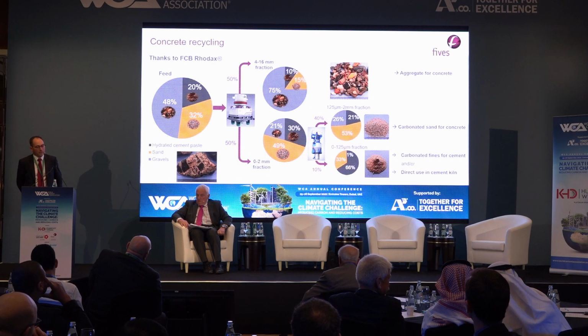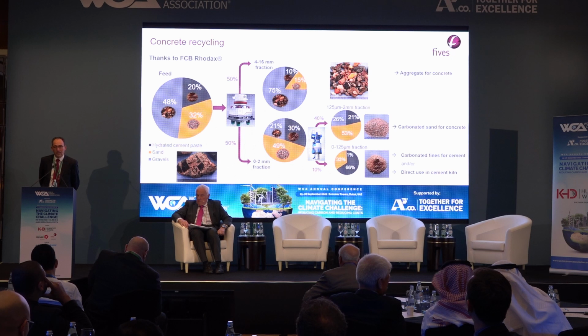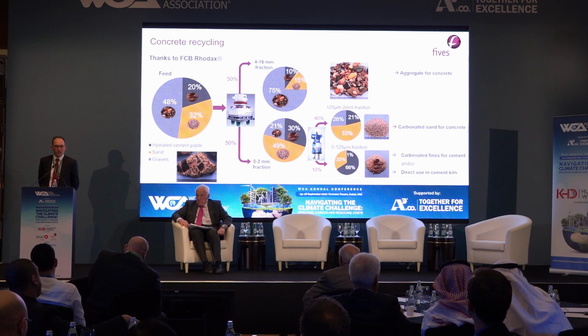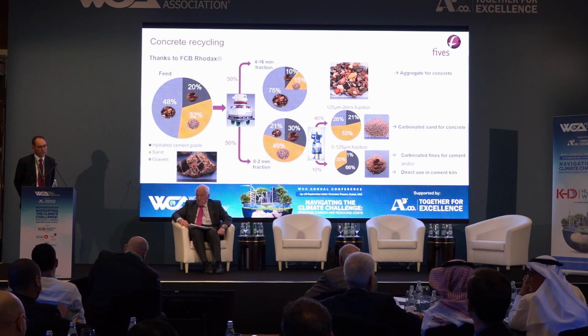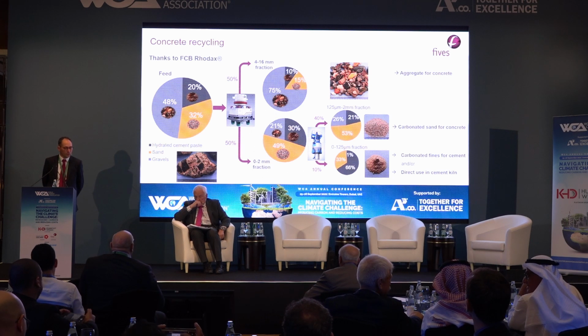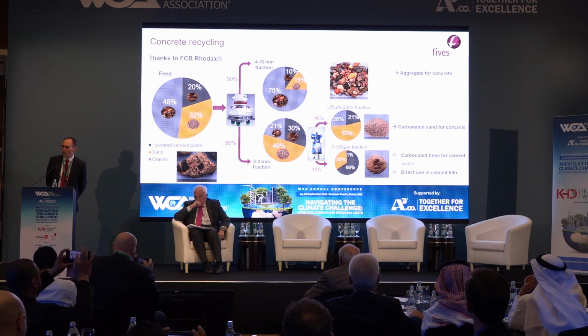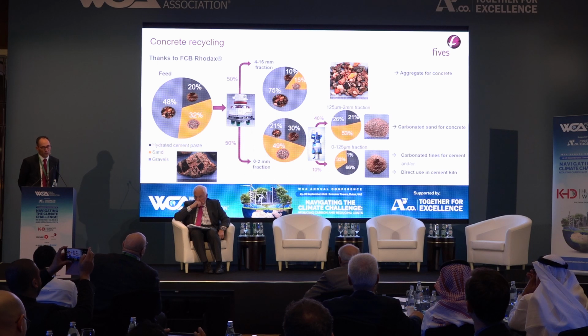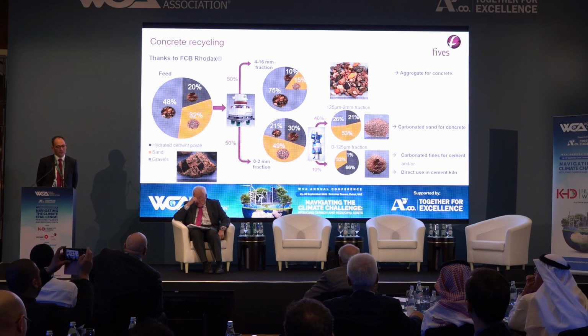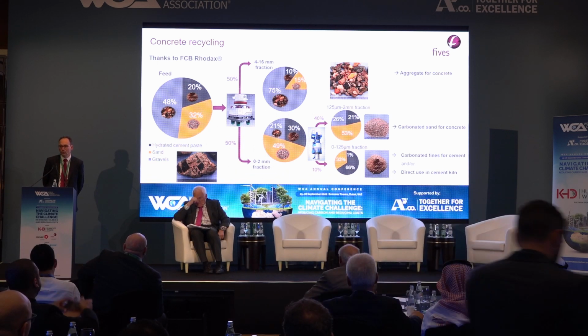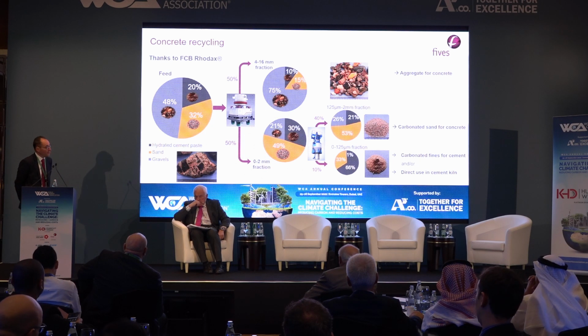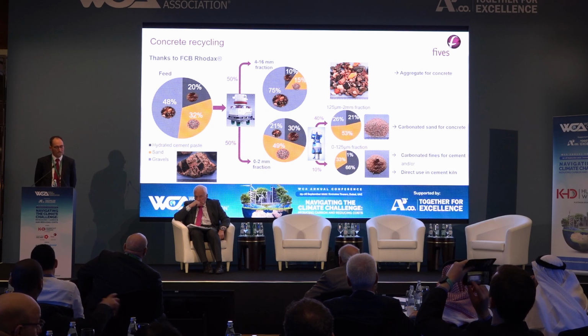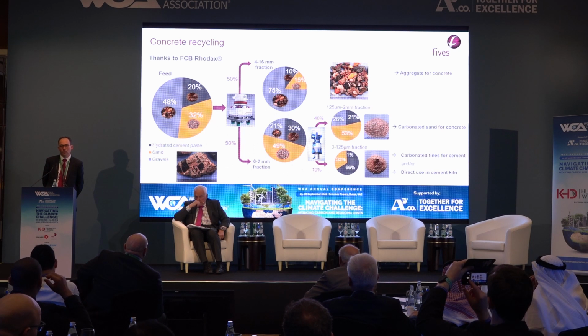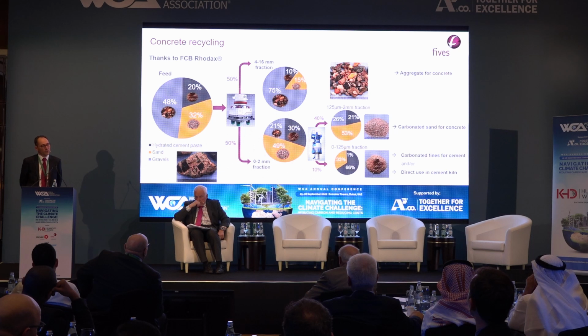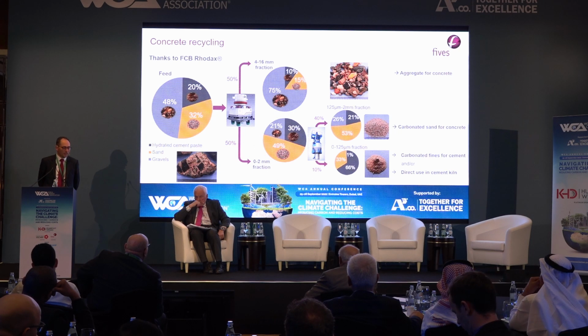So the last baby is the concrete recycling. So we have talked this morning about circular economy. We are typically into the circular economy, because the cement you produce is used to make concrete, and then if you recycle the concrete, then you have high quality aggregate to do concrete again. You have sand to do concrete again, and you have cement paste that you can introduce in your cement kiln in the limitation given by the chemistry of your raw mill, for sure,